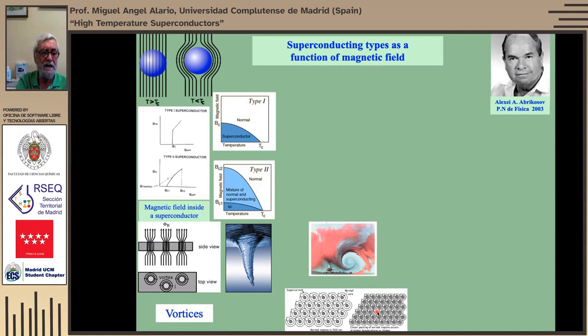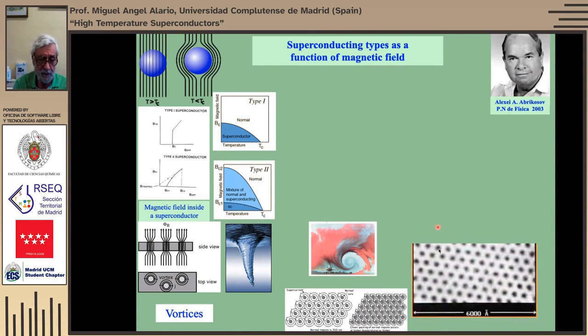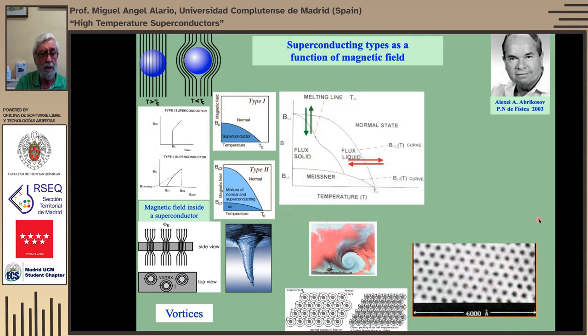Let's wait." And 2 years later, Feynman and others found superfluidity in helium, and it's the same idea. You have vortices of the fluid, and when Landau saw the vortex in liquid helium, he said, "Oh, that's the idea of Abrikosov. Now we can pass our thesis." So it could have been defended 2 years before. Anyway, Abrikosov showed that the vortices should be ordered, and this is the first picture of the vortices of a superconductor, which I think is niobium selenide, and you see that it's a perfectly ordered hexagonal lattice, but this can be more elaborate. So the phase diagram of a superconductor is complicated.